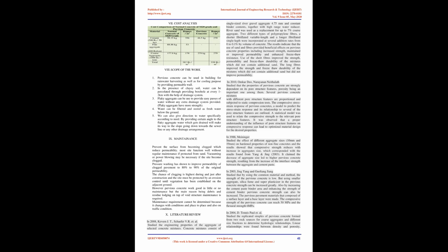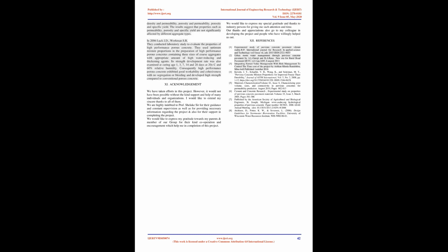The results indicate that the use of sand and fibers provided beneficial effects on pervious concrete properties, including increased strength, maintained or improved permeability, and enhanced freeze-thaw resistance. Use of the short fibers improved the strength, permeability and freeze-thaw durability of the mixtures which did not contain additional sand. The long fibers improved the strength and freeze-thaw durability of the mixtures which did not contain additional sand but did not improve permeability. In 2010, Omkar Deo and Narayanan Neethalath studied that the properties of pervious concrete are strongly dependent